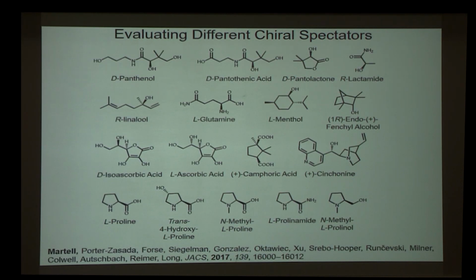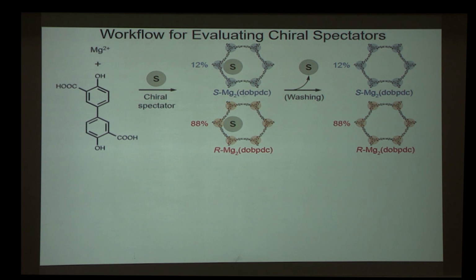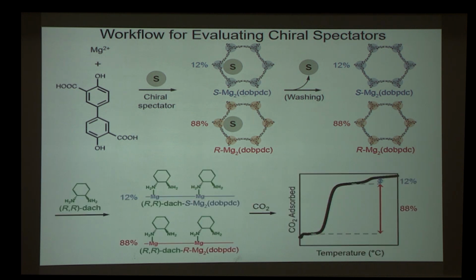So with this straightforward assay in hand, I proceeded to test a number of chiral spectators. These are cheap, commercially available compounds, including a number of amino acids, as well as other natural products. The workflow is as follows. We assemble the MOF in the presence of the chiral spectator, and it's important to note that upon synthesis, the chiral spectator might remain bound to the framework. So I wash extensively to remove any spectator that might be present. This should leave behind just the MOF, which we hope is enantio-enriched. Only now, after all of this has been done, do I introduce the enantiopure diamine and assess CO2 capture to characterize whether I made something enantio-enriched.